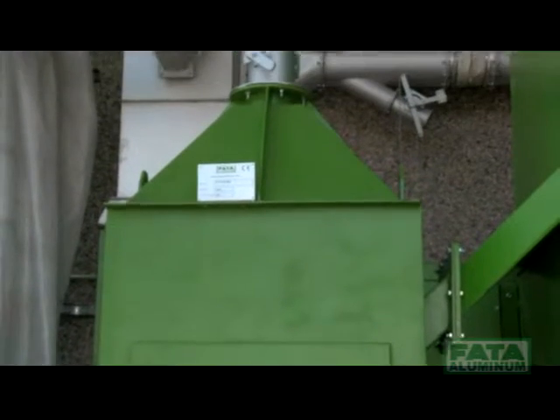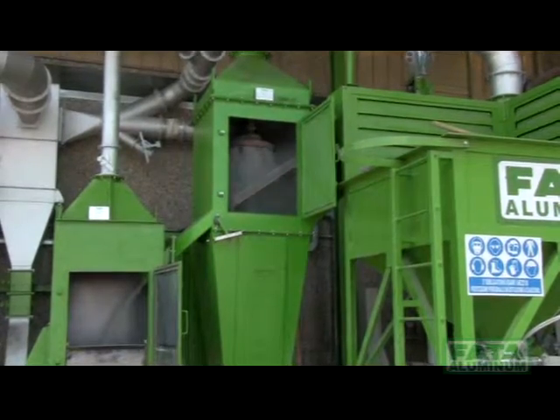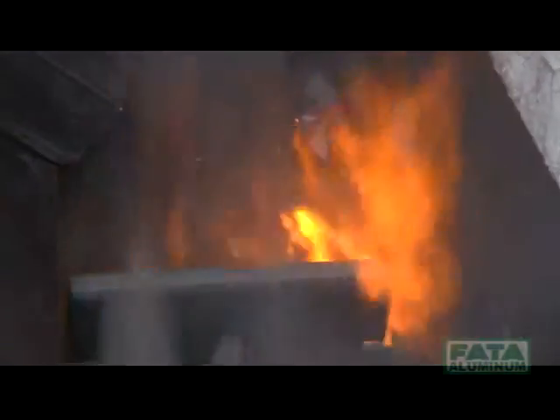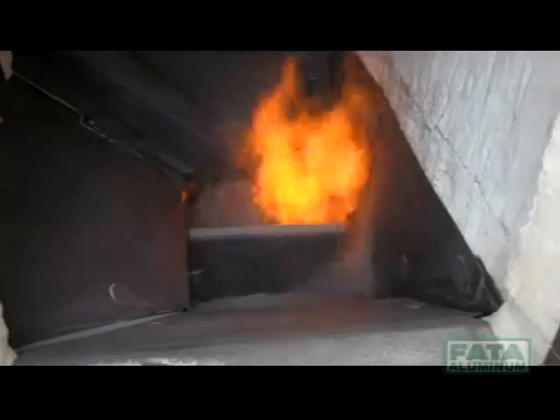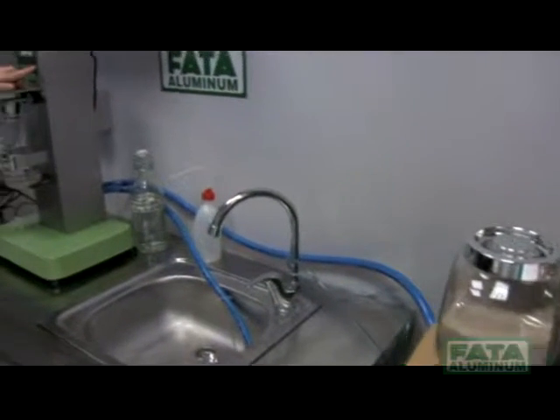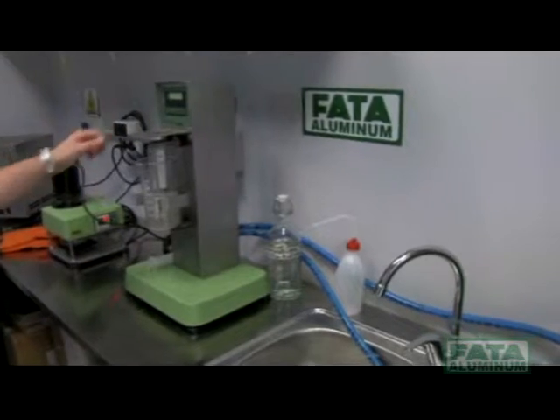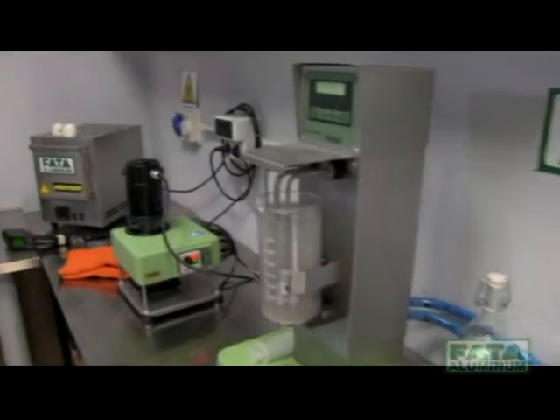A variety of treatments can be done, such as basic mechanical attrition over the sand grain to partially remove clay deposit, or thermal regeneration processes to completely burn all the resin deposit in a temperature ranging from ambient to approximately 750 degrees centigrade. It is also possible to treat the sand mixture with a combination of mechanical and thermal treatments, checking all the effects of small modifications in the reclamation cycle parameters.